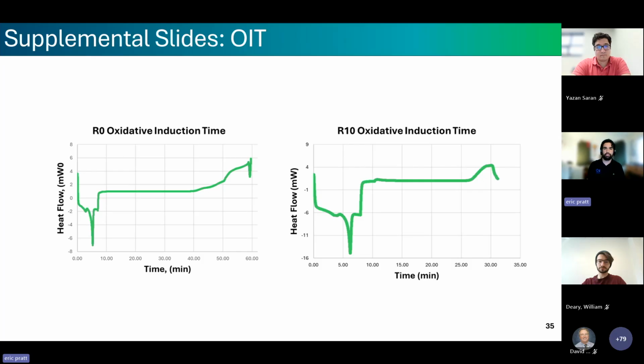And moving on to oxidative induction time, this was conducted on a TA DSC machine. The process here is to load a sample in an open crucible so that it is in contact with air. The DSC measures the heat flow in a material under various heating and cooling conditions, and our test followed ASTM D3895-07. And essentially, the sample is heated at a rate of 10 kelvins per minute until it stabilizes under an inert gas, in this case nitrogen.